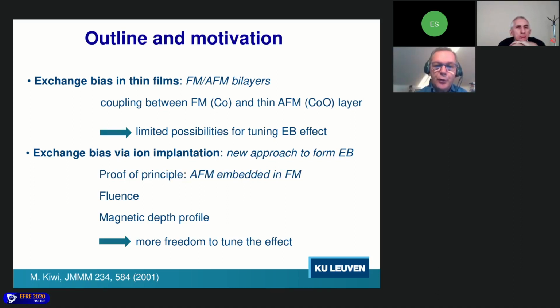So what I will show you today is a number of examples where we first of all show that this really works to create exchange bias. I will talk about the influence of the amount of implanted ions. Then I will show you that we can measure the magnetic depth profile by making use of neutron reflectivity. And in the end, I hope to show you that by modifying the properties of the magnetic layer by ion implantation, there is much more freedom to tune the effect.